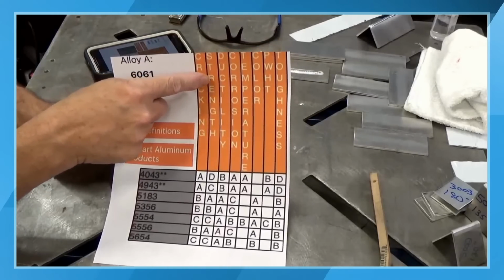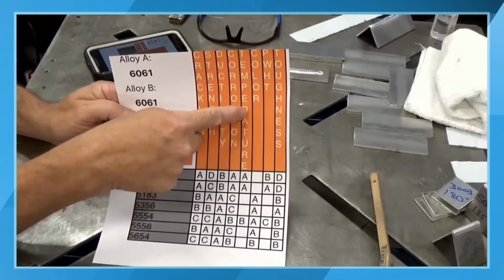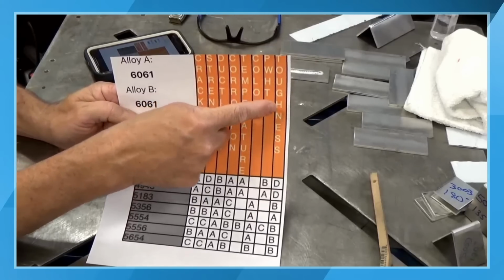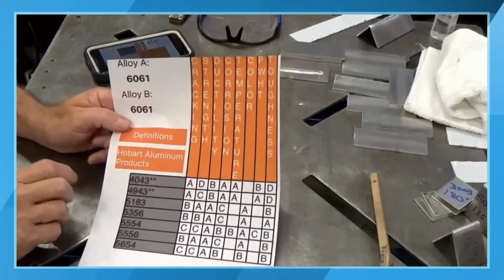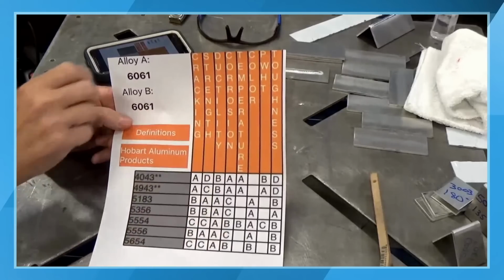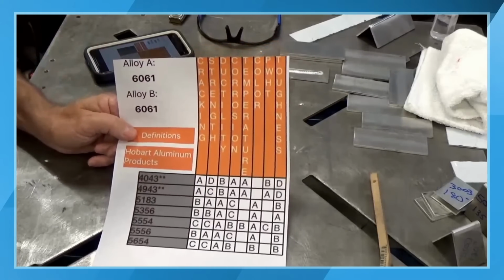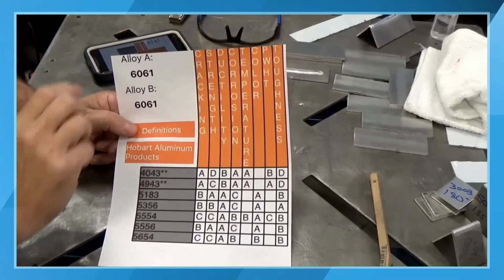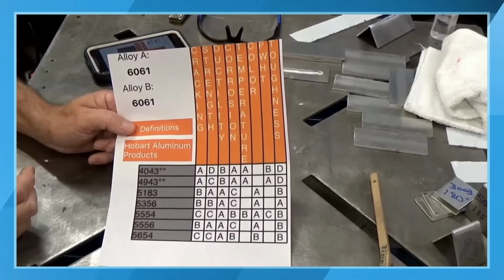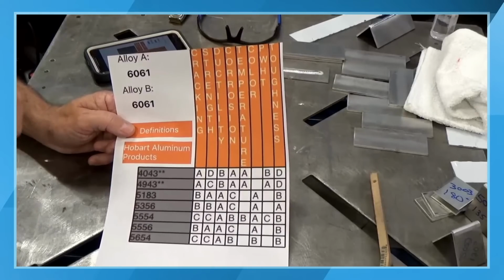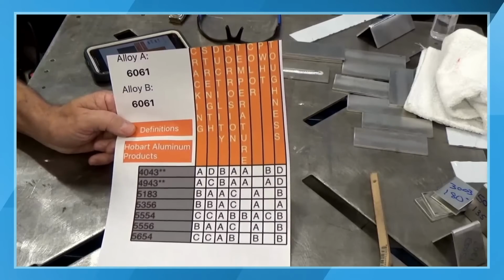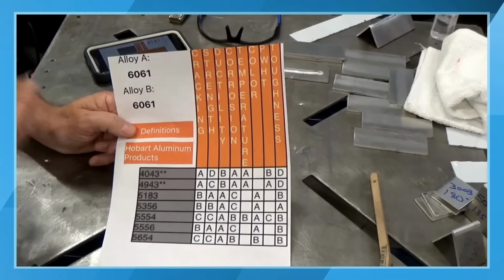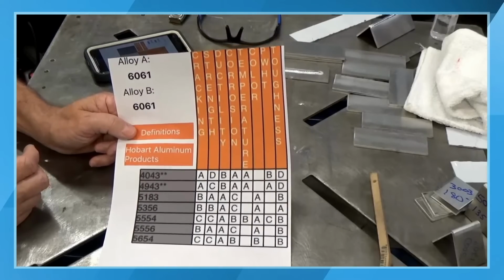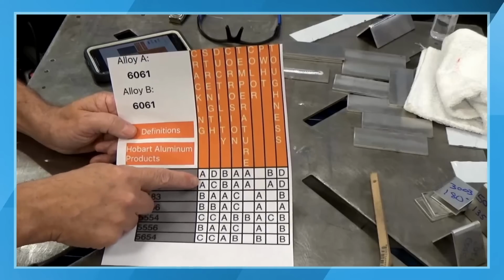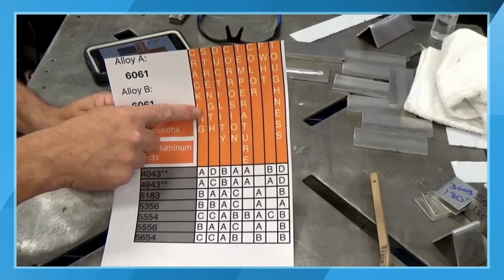So my properties are cracking, strength, ductility, corrosion, temperature, color, post-weld heat treat, and toughness. So what does that all mean, right? So cracking, it sounds self-explanatory, but it's really not. It's hot cracking during the welding. As the weld is cooling, certain filler metals have a tendency to crack, and that grain structure will crack if you're over temperaturing, if you're putting just a little too much temperature on that filler metal. So anything with an A rating is great at resisting hot cracking.